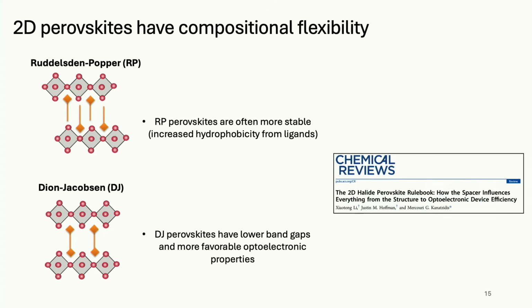perovskites. So you see here, you have the perovskite layer, another perovskite layer. Now you say, how do the molecules arrange themselves? If you only have one ammonium, and then you have some organic stuff, and then you have an ammonium and you have some organic stuff, what's going to happen is, can you see that the peaks of this octahedron align with the equatorial halide of this one, and the peaks of this one align with, they're shifted by half a unit cell. Can you see that? So we have two molecules, and that causes them to shift by half a unit cell. This whole configuration goes by the name Ruddlesden-Popper phase, okay?